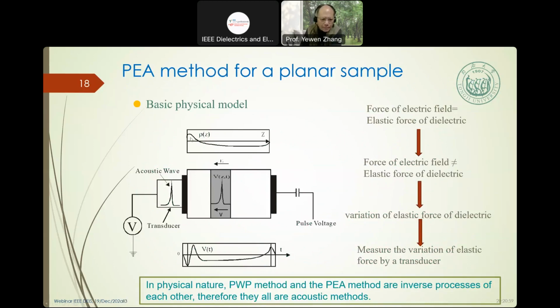We're using a very similar electrical space charge distribution to the last presentation. So we apply the voltage to the sample. It generates the acoustic on this side. So we can get the acoustic measured by voltage. The propagation moves to this side, and we absorb from this side. It moves to two sides, so we only measure the acoustic on one side. You can find the acoustic waves are very similar to the PWP method.